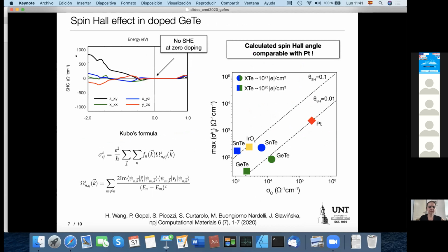Spin Hall conductivity can be easily calculated. It is quite easy to implement Kubo's formula. And here we have 10 non-zero components of spin Hall conductivity based on the space group and symmetry of this material. 4 of them are independent, so I plotted them here. But as I mentioned just a second ago, here we don't have any states for zero chemical potential. So we have to tune this chemical potential to reach some non-zero spin Hall conductivity.